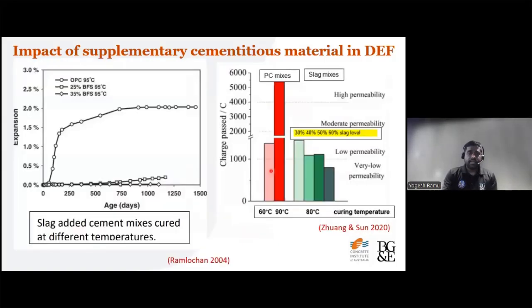Is it only fly ash that does this? No. If you see some examples from other researchers who studied slag systems as well, the plain OPC system has very high expansion when it's cured at 90-95 degrees Celsius, but with 25 to 35 percent blast furnace slag, you can see the expansion is almost eliminated here.